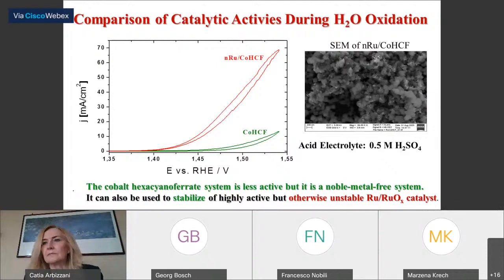Over here, I presented a comparison of catalytic activities during water oxidation. And as is shown on the graph, the hexacyanoferrate system is less active than the modified system, but it's a noble metal-free system. It can be used to stabilize highly active but otherwise unstable ruthenium oxide catalysts.